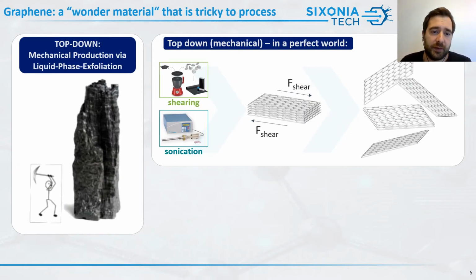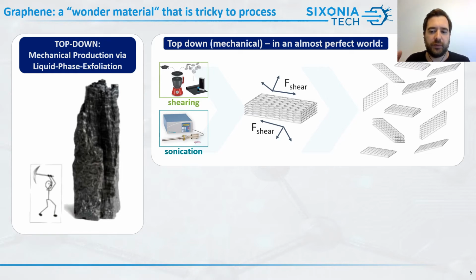One example of a problem with mechanically exfoliated graphene is this: in a perfect world, you apply shear forces to the graphite, much like in the original Nobel Prize experiments with the Scotch tape, and these shear forces align nicely parallel to the graphite sheets. But in the real world, if you apply them using a sonicator or a shear mixer, they will act in random directions. So they do not only exfoliate the graphene, but the exfoliated material will also be cut in the middle, for example. So the thinner the particles you get, the smaller the lateral size will get, which doesn't have to be a problem yet.